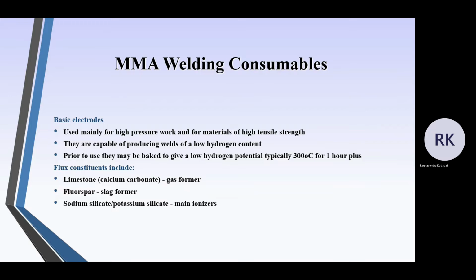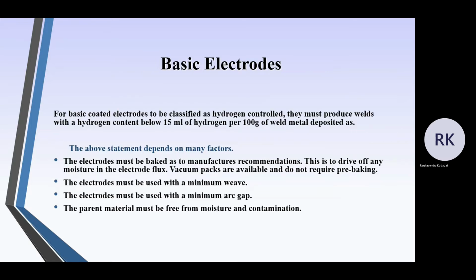Then flux constituents include limestone, which is basically calcium carbonate. Fluorspar is also a slag former, and again sodium silicate and potassium silicates are the ionizers. Coming to basic electrodes, the coating will be classified as hydrogen controlled. They must be produced with hydrogen content below 15 ml of hydrogen per 100 gram of weld metal deposited.